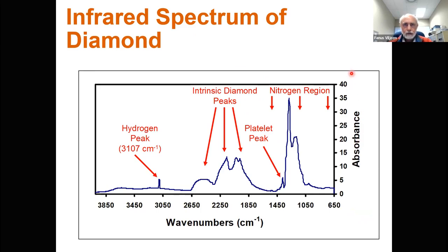Still on the subject of infrared spectrometry of diamonds, this is a typical infrared spectrum of a nitrogen-containing diamond. And along the horizontal axis, we have wave numbers, which is essentially the number of cycles that you have in your infrared region of the optical spectrum per centimeter. On the vertical scale, we have absorbance, which is essentially how much of the infrared radiation is absorbed by the diamond as the beam passes through the stone.